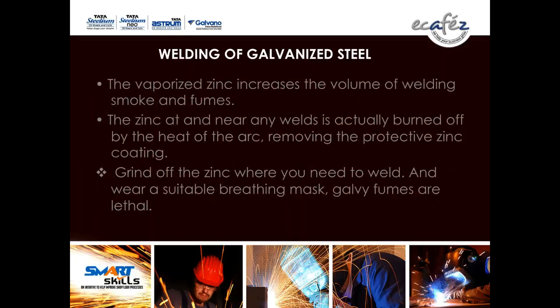The vaporized zinc increases the volume of the welding smoke and fumes. The zinc near any weld is actually burnt off by the heat of the arc, removing the protective zinc coating. Grind off the zinc at the interface of the weld, wherever you have to weld, if your welder is skillful and knowledgeable, and wear a suitable breathing mask, because mind that galvanized fumes are lethal.